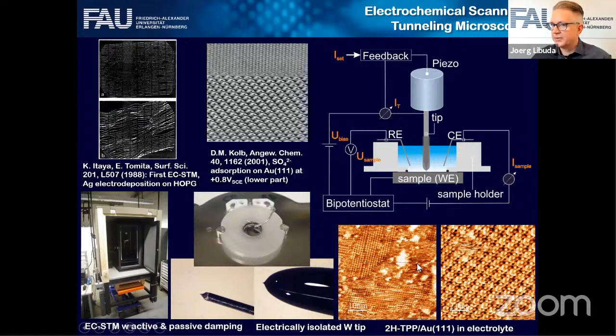The experiment is old. It's more than 30 years old. It was shown more than 30 years ago that such experiments are feasible in principle. And then after a very short time, it was shown that you can really achieve atomic resolution with this experiment under electrochemical conditions, which is beautiful. In principle, it is relatively straightforward to achieve atomic or molecular resolution with this type of experiment. And here's an example, for instance, of porphyrin molecules sitting on an electrode.